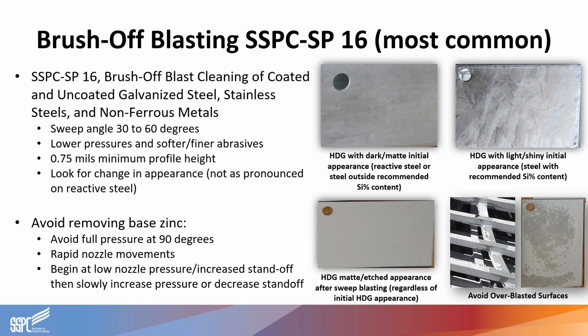So someone unfamiliar with hot dip galvanizing will want to look out for that etching appearance as well, to make sure the entire surface has been sufficiently cleaned. What you really want to avoid is shown here on the bottom right. This is blasting at 90 degrees head-on with harder, larger abrasives and at typical pressures and standoff distances you would use to clean bare steel.